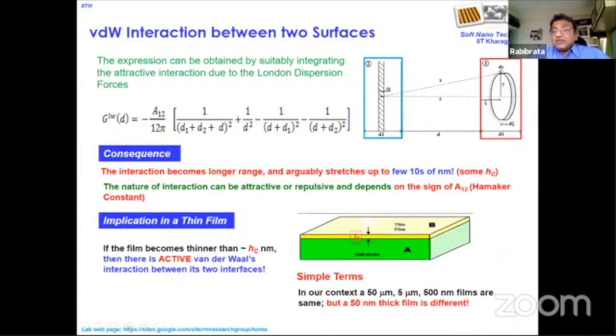So what sort of thickness are we talking about? We just talked about how between two surfaces, the van der Waals interaction stretches by about 100 nanometers. So if the film is thinner than 100 nanometers, there is an active non-zero interaction between these two interfaces. This is what is called the disjoining pressure. Based on the material of the film, based on the spreading coefficient, this interaction can be negative or attractive or repulsive.